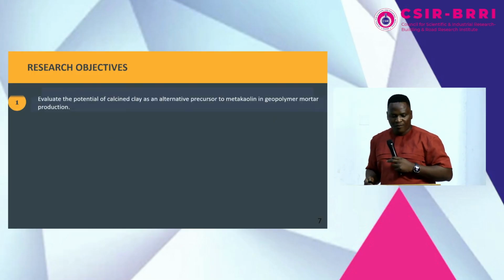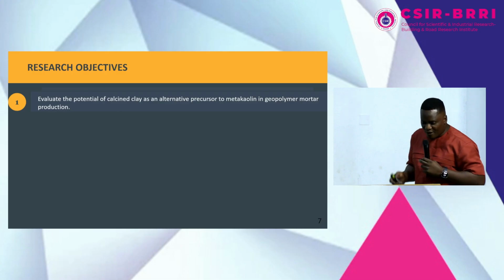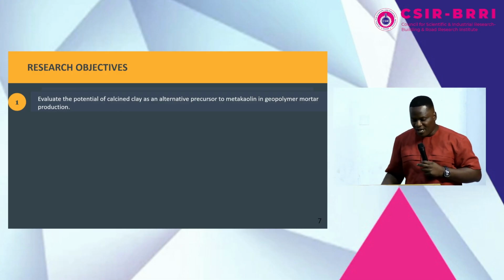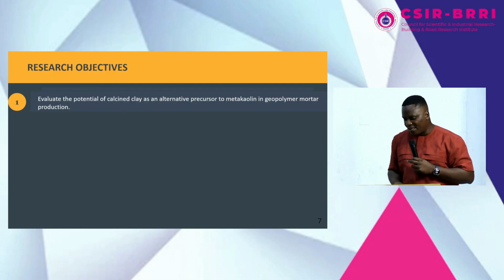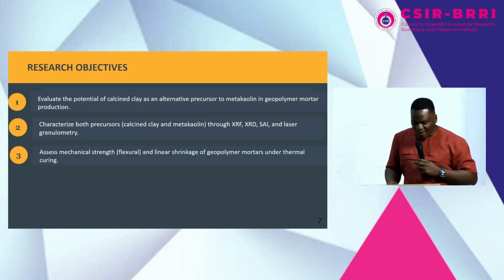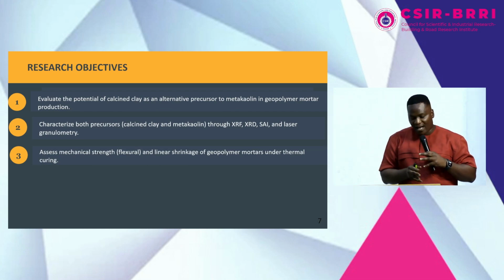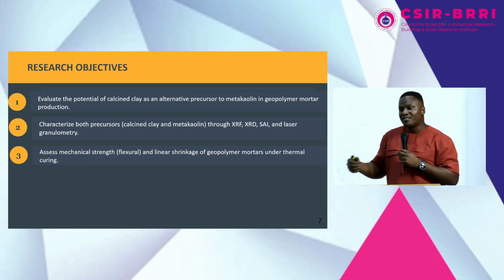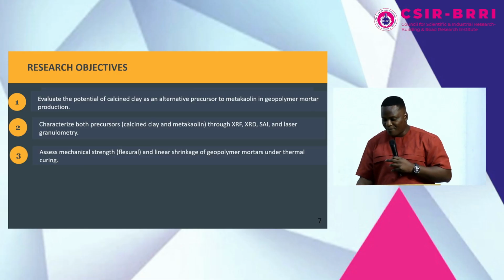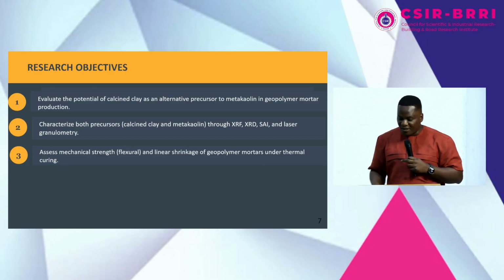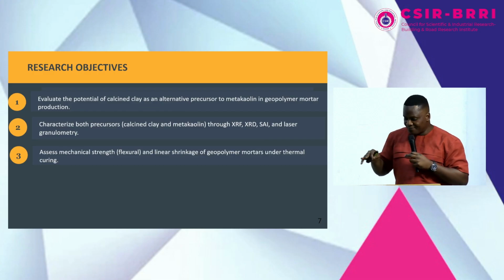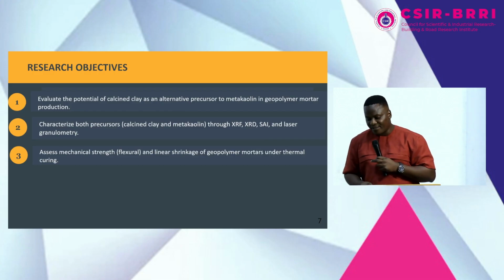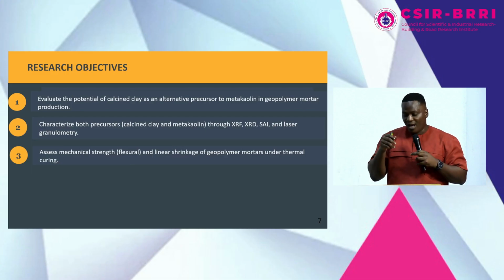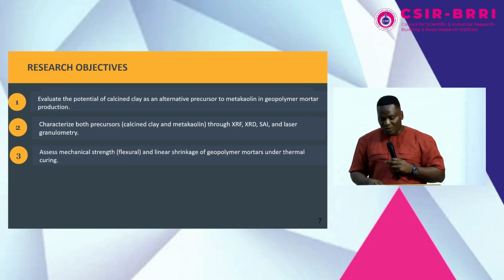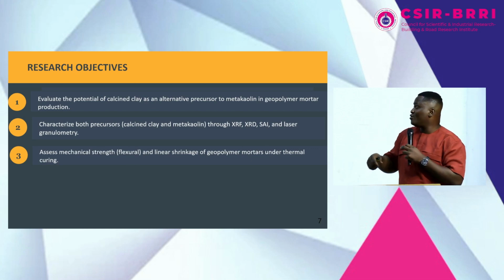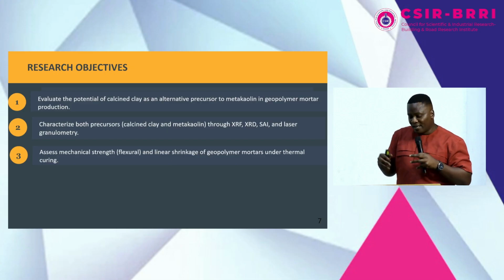All right. Okay, so the research objective is, first of all, to evaluate the potential of calcined clay as we have it here in BRI as an alternative precursor to metakaolin in geopolymer mortar production. And also to characterize the 2 precursors, that's the calcined clay and the metakaolin, through XRF. The XRF is a way of looking at the chemical composition of the material. Then XRD, that's X-ray diffraction, and that also takes a look at the mineralogical phases of the material. And strength activity index, basically talking about strength. And all these things have a role to play in achieving the kind of results we are looking for. And also laser granulometry. This is used to look at how the granules are compacted in the material.